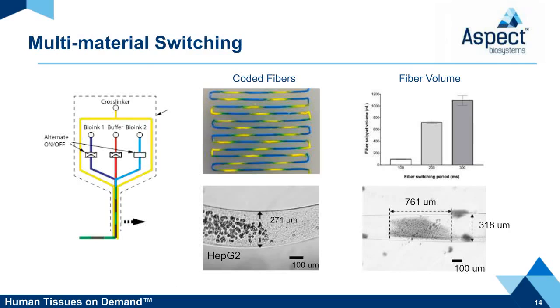Fiber composition is also precisely controlled. Because each material channel is valved, we have control of material flow and can turn material channels on and off, allowing us to rapidly switch between materials. We can create individual material packets within a fiber of a volume of around 2.5 nanoliters. This enables the precise deposition of small volumes of precious cells.